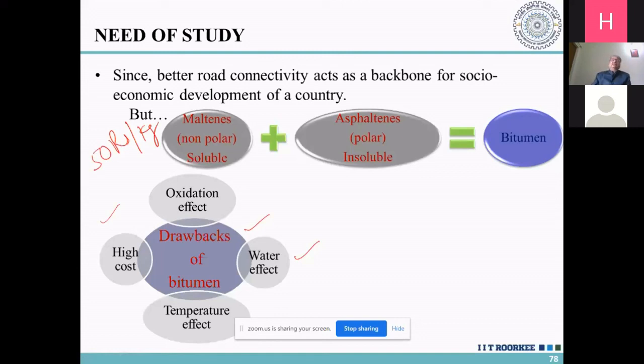And the temperature effect: as I said, it is in use because its properties vary well at different temperatures. But when this temperature variation effect is too much, then it becomes the negative part. For example, in the summer season, if the temperature is high, it becomes soft and bleeding of the bitumen starts. Similarly, during the winter season, when the temperature is very low, it becomes very stiff and cracking starts.